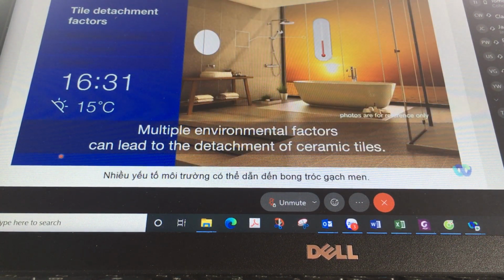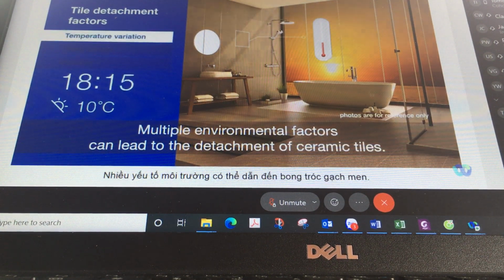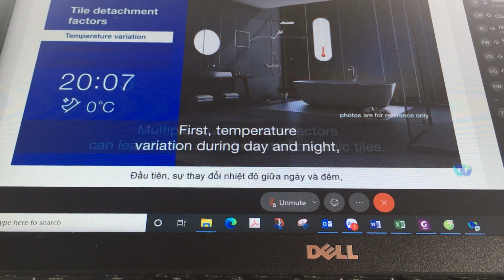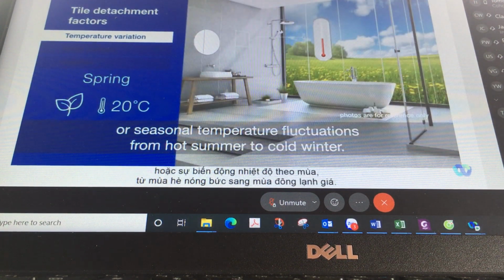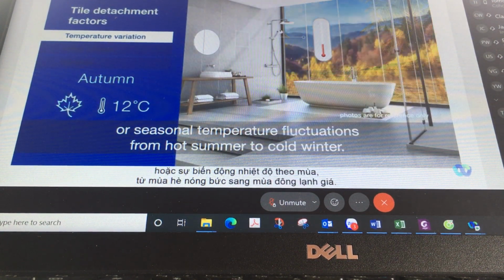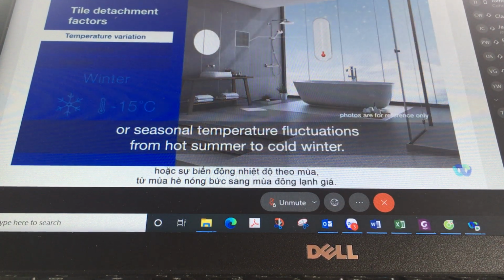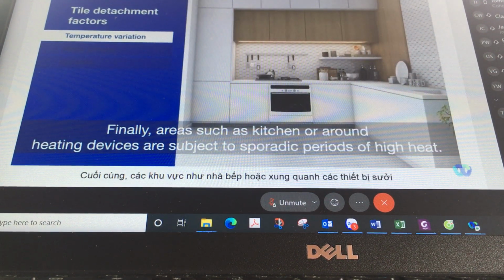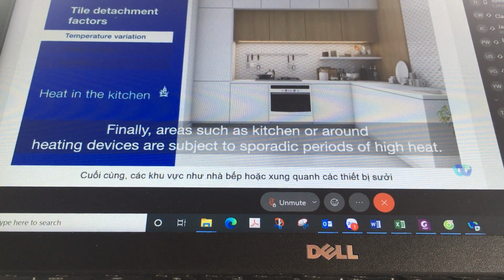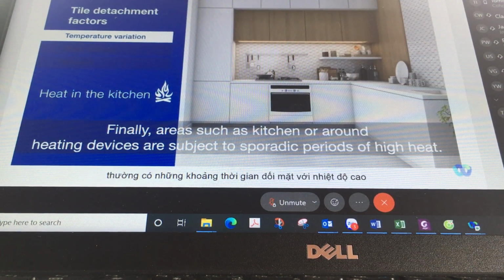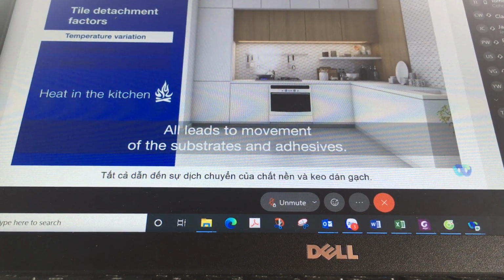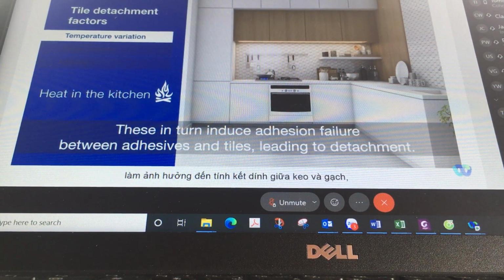Multiple environmental factors can lead to the detachment of ceramic tiles. First, temperature variation during day and night, or seasonal temperature fluctuations from hot summer to cold winter. Finally, areas such as kitchens or around heating devices are subject to sporadic periods of high heat. All lead to movement of the substrates and adhesives. These in turn induce adhesion failure between adhesives and tiles, leading to detachment.